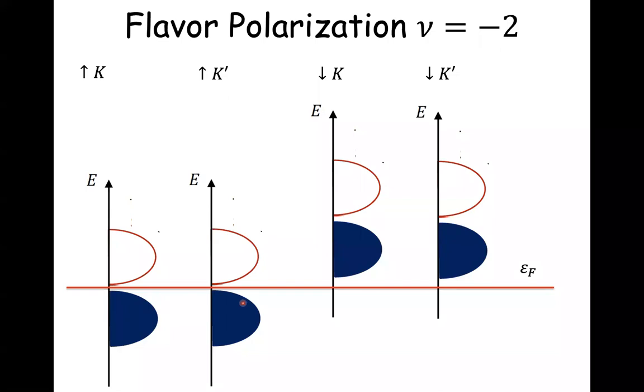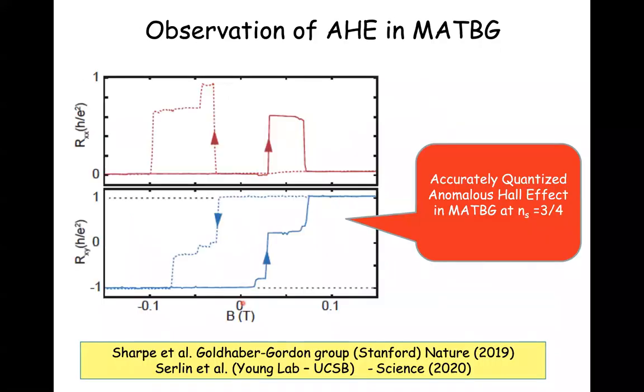For example, if only one of the four valence bands is occupied or only one of four is empty, you will only get a contribution from one valley, and that can be understood, that will give a quantum anomalous Hall effect. And indeed, this was quickly seen in experiments from Aaron Sharpe, from David Goldhaber-Gordon's group and collaborators. And they saw a very large anomalous Hall effect in this system that could be changed in sign. And now this quantum Hall effect has been shown to be nicely quantized, and I think it will turn out to be perhaps our best experimental example of the quantum anomalous Hall effect.